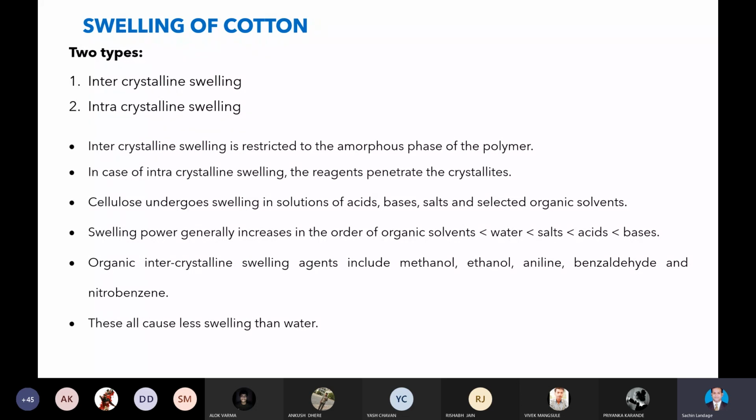See, one simple process which you are going to perform is mercerization, which you perform at a concentration of 17.5 to 22.5% NaOH, or 48 to 52 degree Twaddell. In that, if you put the fiber, you will observe tremendous shrinkage. The fabric will become just like elastic rubber.